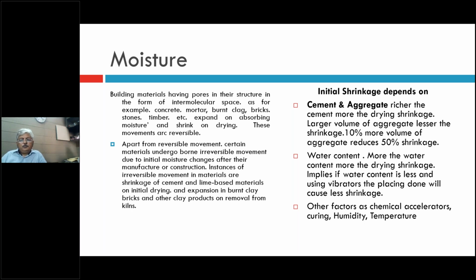These are the factors which definitely cause the cracks to happen, because if we are constructing a home in quite a dry kind of atmosphere, the cracks will be evident quickly, because moisture is required to take care of the chemical reactions which are happening within the cement in contact with the water. So that way they keep on happening for up to 1 month. That is why if an RCC slab is done in monsoon times, it will give you much more durability.